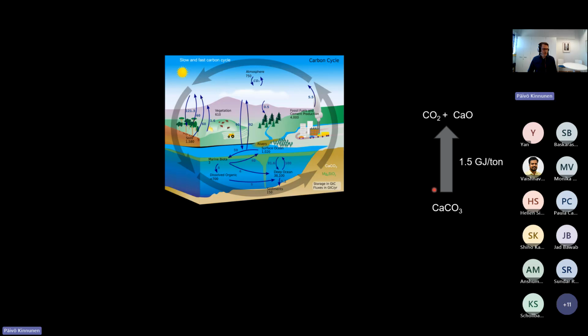So okay, this is the current situation. So we're putting CO2 in the atmosphere, and actually, if you look at it in terms of grams, this is about the same amount of CO2 as calcium oxide that's produced in this reaction. So you can think of CO2 as being one of the main products in cement production. It's just that it's invisible, so we don't see it, and that's why we have been able to do it for so long without realizing it. So what we could do, in order to reverse this, or at least mitigate it, is something like a reverse reaction, where we take an oxide and react it with the CO2, so that we get a stable mineral.